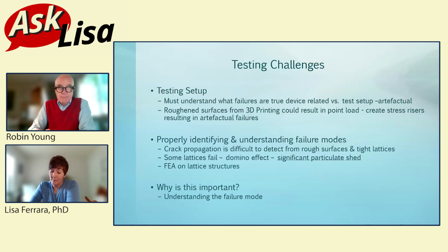Every implant was inspected prior to testing, whether it was printed or not. But printed in particular, because of those surfaces, you need to understand, is there going to be a crack that propagates? And how do I know? And sometimes if the printing, especially back then, was really rough, it was hard to tell if it was a crack, if it was there, did it propagate, if they coated it in any way. So that was an incredible challenge.